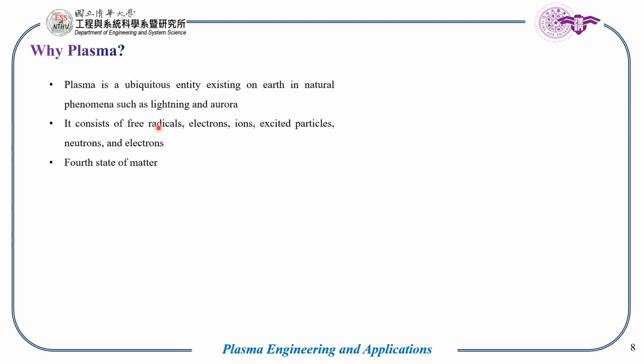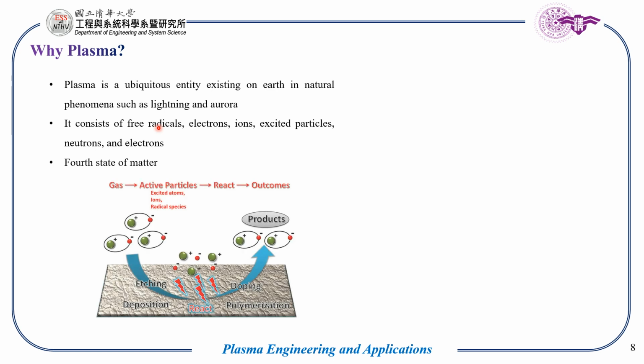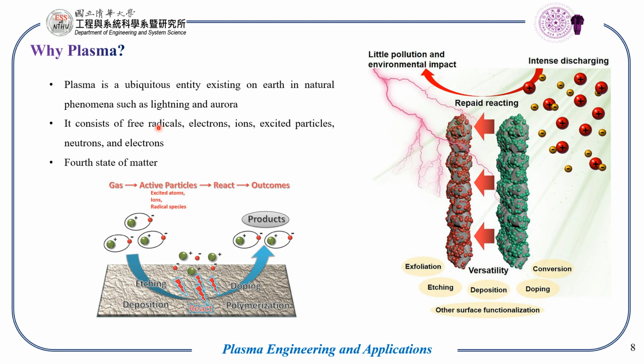So why are we using plasma engineering, and what is plasma? Plasma is the fourth state of matter, and it consists of free radicals, electrons, excited particles, and neutrons. When these energetic radicals go through the surface of any material, they hit the surface and create many defects or vacancies, which help in making the material more active, which is more helpful for hydrogen generation as well as for oxygen evolution, and different reactions become faster. Thereby plasma engineering has been helpful for increasing the efficiency of different photocatalysts or electrocatalysts by increasing the defects or vacancies created on the surface or interface of the different materials.